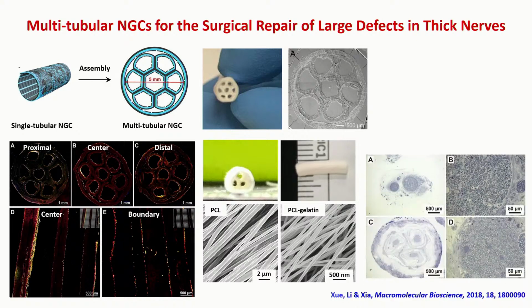We also have started to evaluate their efficacy. We first started with this tri-tubular conduit because the model we used was just a rat, which has relatively small nerves. We cannot accommodate 7 conduits, so we just use 3. As you can see over here, these are the 3 individual conduits. And this is the control group, the autograft. You can see the final results. This is a cross-section of the repaired nerve in terms of density of nerve fibers.